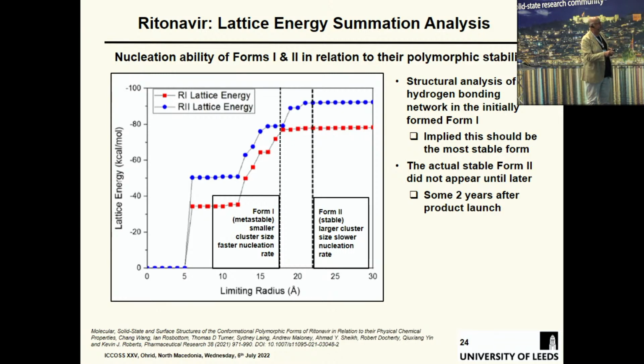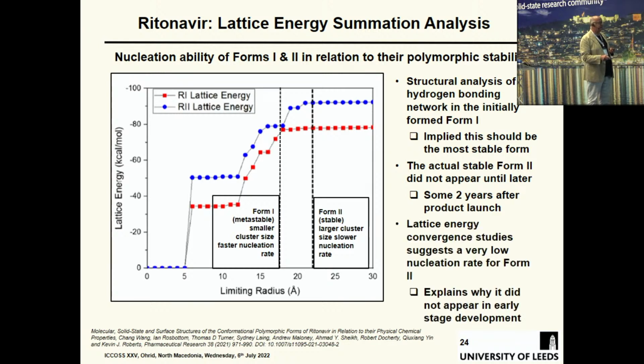And so the lattice energy convergence with size explains why it did not appear in the early stage development, because it's very soluble. If you ever dissolve this thing in ethanol, you can't get it out of solution. It's like a soup. And so you naturally tend to drown it out with an anti-solvent, but then you've got to be really careful to keep the supersaturation down.